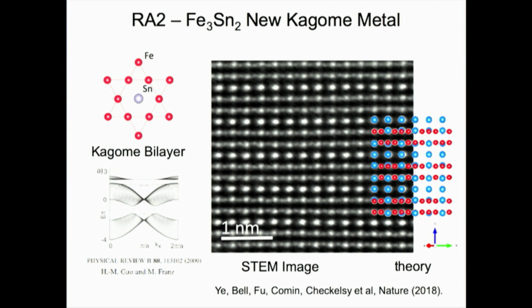Let me show you an example of a new material that had a property that they wanted, and then they predicted what material to make and went ahead and did it and characterized it. And this iron tin material makes something that's called a Kagome lattice, which is actually, if you're making bamboo baskets in Japan, there's a particular pattern that they do that looks like a star, an iron star with a tin in the middle. And the reason they did that was to have a flat energy band where you can localize the electrons, where the energy doesn't depend on the momentum, and that's shown here.